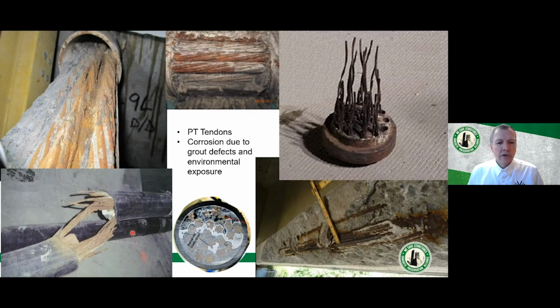And unfortunately, corrosion continued at the interface between the old and the new grout, and you can see that the strand, or the tendon here, has essentially been severed at the location where the two different grouts meet. We can talk about that later if you're interested.